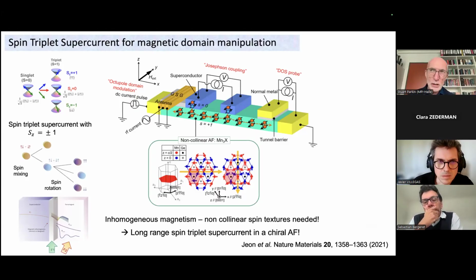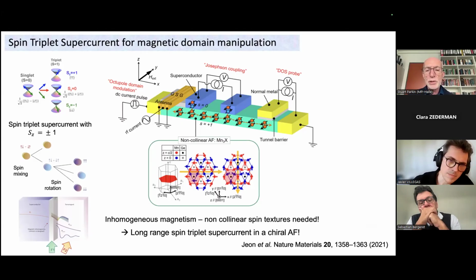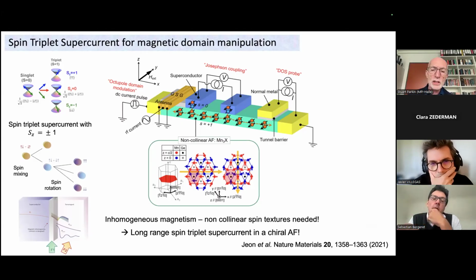It's metallic, but it also has a very interesting Berry phase component, which is an effective magnetic field that the system generates. And this leads to this type of material showing interesting properties such as an anomalous Hall effect. Even though there's no net magnetization in this system, due to frustration, the manganese moments are oriented in the plane of this system, but will be oriented at 120 degrees to each other, as you can see in this cartoon.